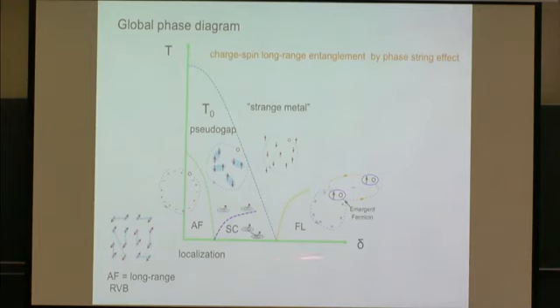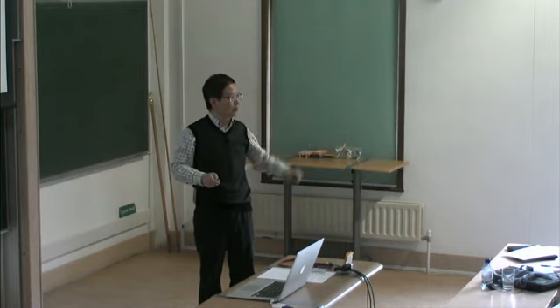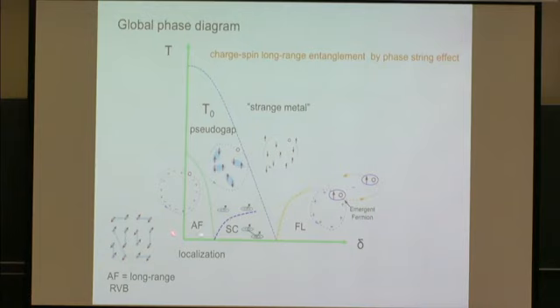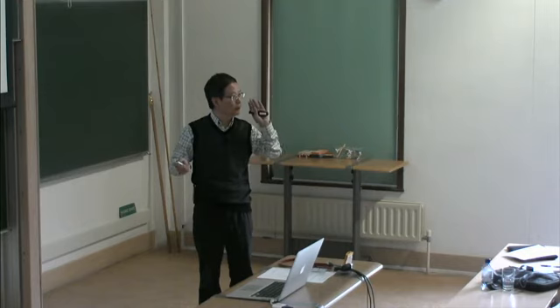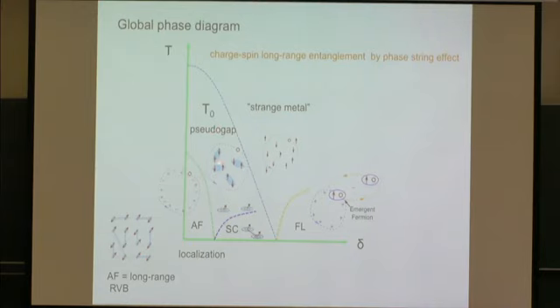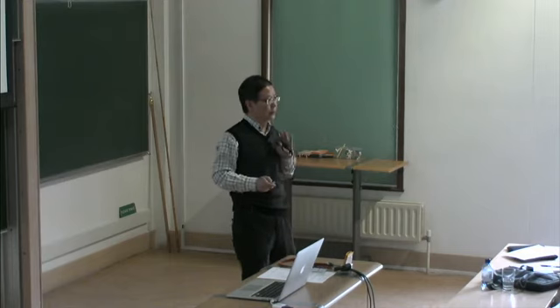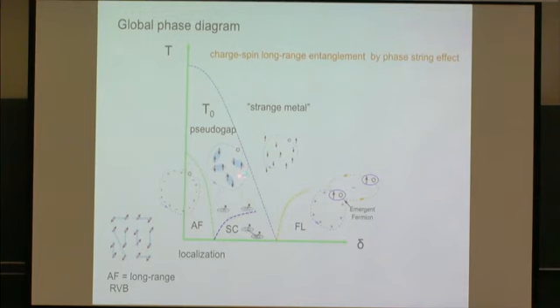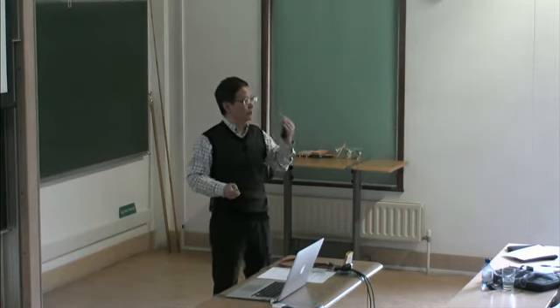This is temperature versus doping, at a very small doping. We know this state is a long-range antiferromagnetic order state, and then you dope holes, the hole will pick up some long string sign, making it self-localized, until some critical point where the ground state will be driven into a short-range order state. Once it becomes short-range ordered, the hole's phase disordering will be removed, such that it will become a superconducting phase. But this superconducting phase is not a simple spin liquid.